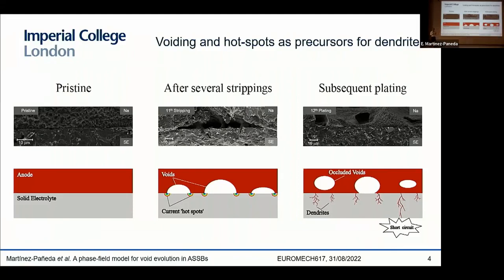And understanding this voiding process is critical because whenever you have those voids, as you can see here, you generate these current hotspots, these localized regions in the electrolyte near the edges of those voids where the current accumulates, where you have high localized current density. And in these regions of high localized current density, you have an exacerbation of plating, and this additional plating leads to the propagation of those dendrites that go on to cause the short circuit and the cell death. So we need to understand how those dendrites evolve to be able to predict.